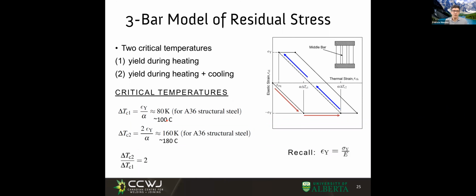And when you reach something of the order of 180 degrees C, you're not only reaching plasticity, but when it cools down, it's plastic again. This is pretty radical, right? To realize that we're going to end up with these residual stresses even at lower temperatures, way below the bead. The edge of the bead has a maximum temperature of, say, 1500 degrees. And we say that yield happens at 100 degrees C, way outside the bead.